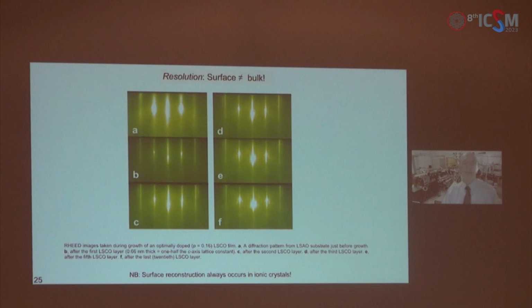But how do we reconcile all this with STM results? We may get a hint from RHEED, reflection high energy electron diffraction. This is a surface-sensitive characterization technique that we use to monitor the film growth in real time. So in fact, we watch RHEED movies. I watched that movie more than 5,000 times so far.